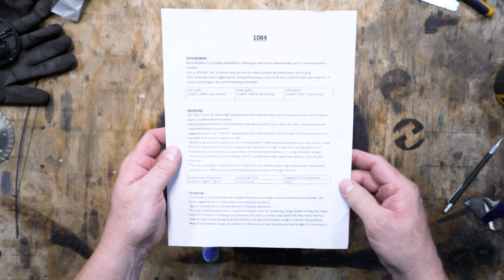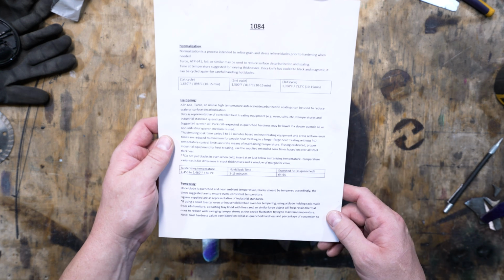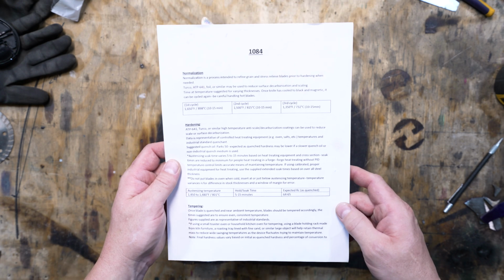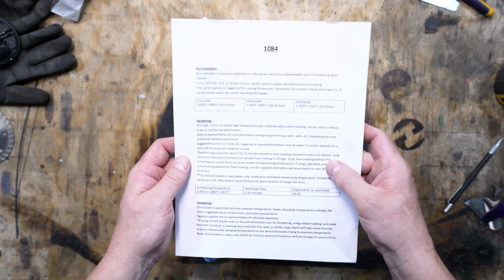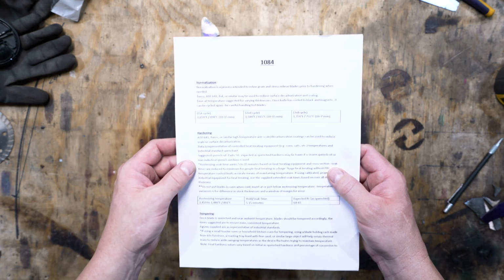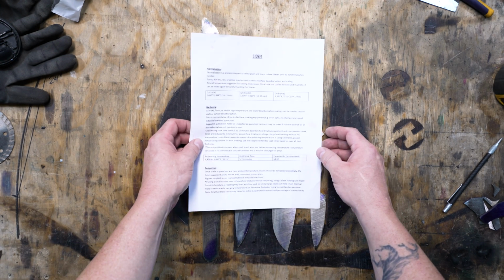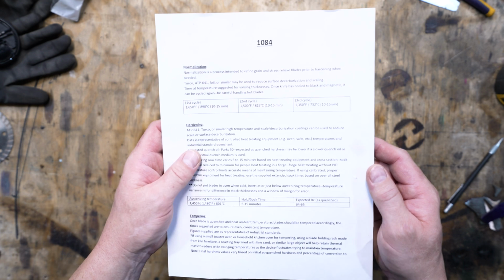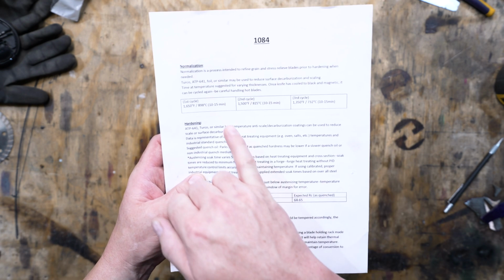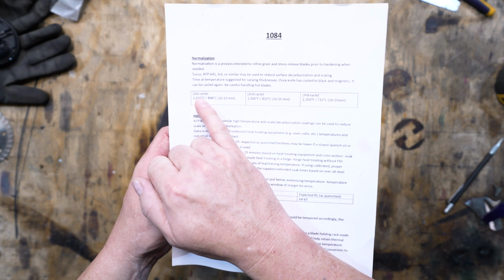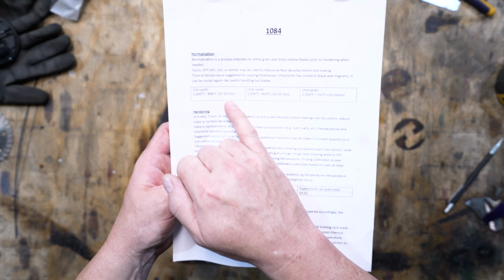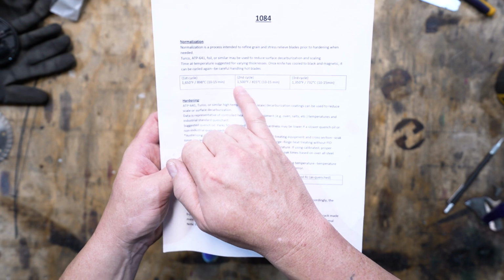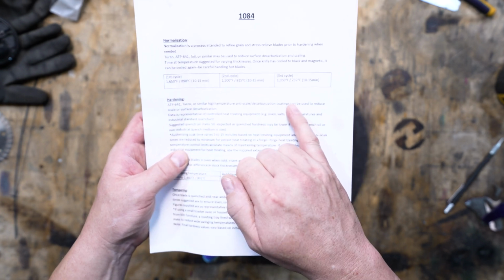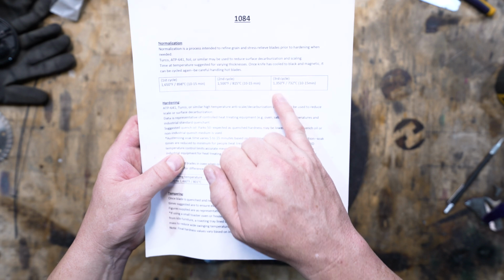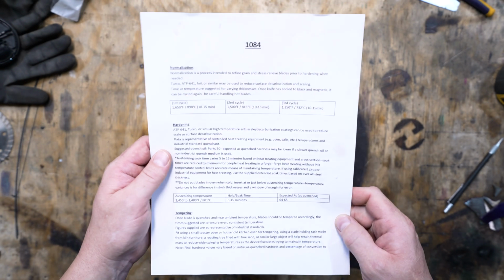This is New Jersey Steel Baron 1084 and 15N20, so I'm going to heat treat as though the whole thing's just 1084. So on here you can see they've got a normalization temperature and a length, a soak cycle. So the first cycle 1650 for 10 to 15 minutes, second cycle 1500 for 10 to 15 minutes, and the third cycle is 1350 for 10 to 15 minutes. So that's what I do.